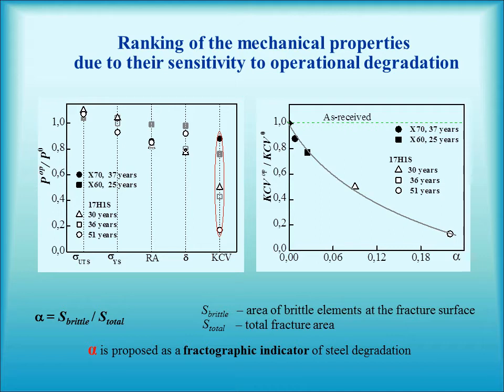Revealed structural and fractographic features of degradation for the tested materials after impact tests were quantified using a software elaborated in our institute. As a result, we introduce a parameter alpha as a ratio of the area of brittle elements detected at the fracture surface to the total fracture area. The established relationship alpha versus relative changes in KCV parameter allows ranking operated pipeline steels according to their current state, degree of embrittlement, regardless of their strength, time of operation, and service conditions. We can see that the points attributed to different steels lay on the one curve. Alpha, in turn, is proposed to consider as the quantitative fractographic parameter of steel operational degradation.